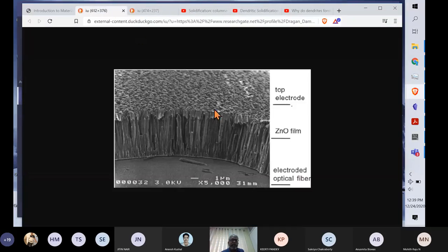examples of this stuff. Okay, so here is an example of a zinc oxide that has been grown on a substrate. And you see all these columns which are going directly up here. And that's because along that direction, the growth is much easier. And therefore, even though right at the bottom, many different crystal orientations would have been formed, pretty soon, the ones that have the favorable orientation grow quite fast. And so the top surface is here, and it is basically polycrystalline.